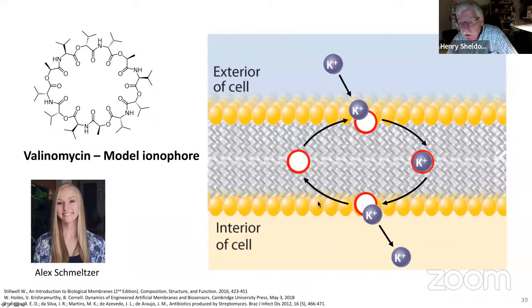So here's a bilayer that we have. I'll show you the support system, which is important to do these single molecule measurements. And you have valinomycin, and the bilayer is depicted by this red circle. If you apply a voltage across the bilayer, the valinomycin can bind to a potassium ion at this top interface, transport it through the bilayer, and release it at the opposite interface, and then diffuse back to the top one and pick up another ion.